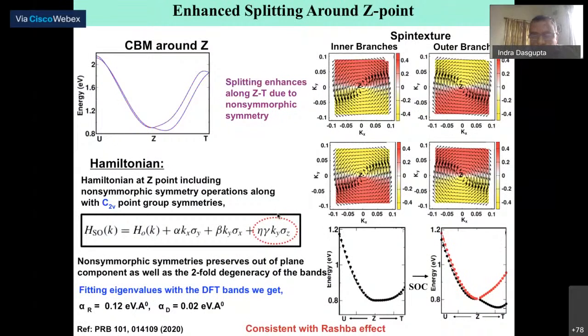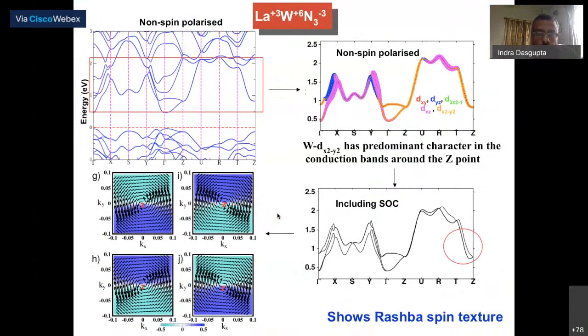Well, so far so good. What I want to tell you as I move along is that along the Z point, the spin texture is of the Rashba kind with a kz component, with a large splitting, primarily driven by the non-symmorphic operation. But an important thing I'd like to take along is that the band which splits has a predominant tungsten dx²-y² character.